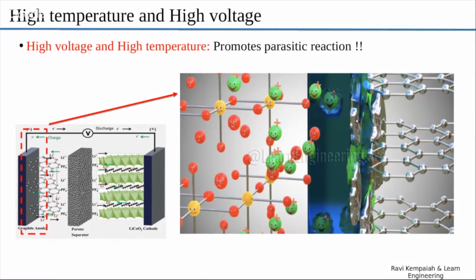And in fact, if you start using a Nissan Leaf on a highway, cruising at 70 miles an hour for 2 hours, it actually shows an indicator that it's time to slow down. And you can't really fast charge after cruising at 70 miles for 2 hours. The Leaf doesn't let you DC fast charge, because the system knows that if you use it on the highway and then start fast charging, it leads to unnecessary byproducts and chemical reactions. This is just mind-boggling to me.